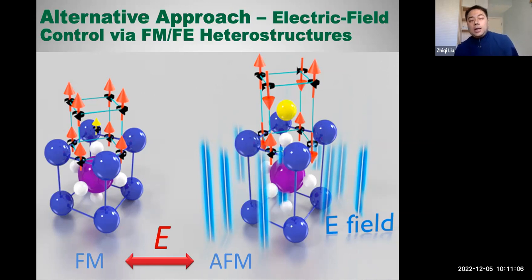And then if we can combine the ferromagnetic materials with ferroelectric functional oxides, we can use the electric field generated piezoelectric strain to control the magnetization of the ferromagnetic materials. In this way, we could generate a new approach to writing the information.